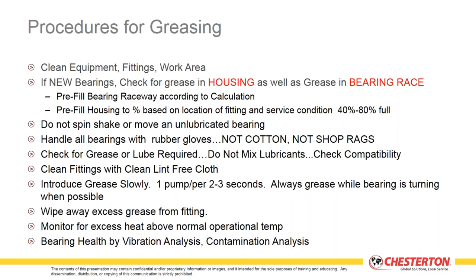Bearing housings are filled between 40 and 80% of the entire volume based upon service condition and where the zerk fitting is on the housing. We always tell our guys, don't spin or shake or move an unlubricated bearing. When you take a bearing from the package, it is not properly lubricated. Maybe a light film of storage oil, that's it. Personally, for myself, any bearing that comes into your warehouse should be lubricated with a good grease and then stored, to possibly allow for vibration of the shelves or things that are handled as the maintenance guys go to install them.